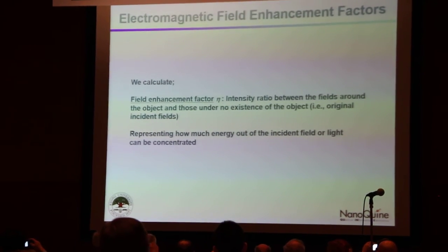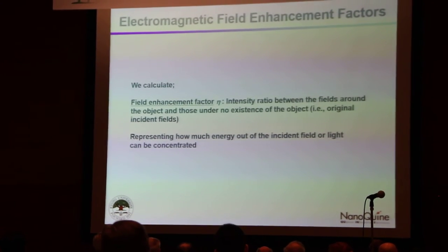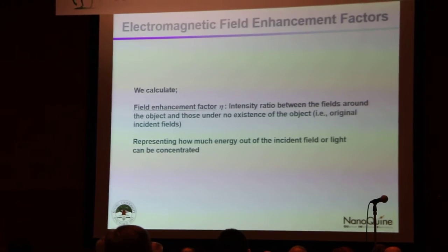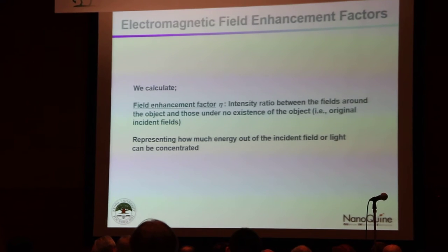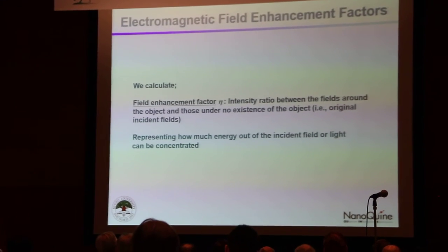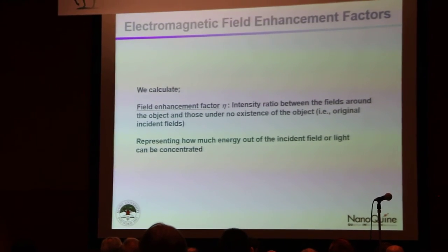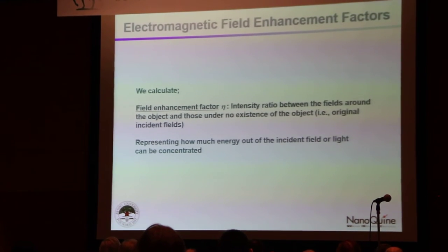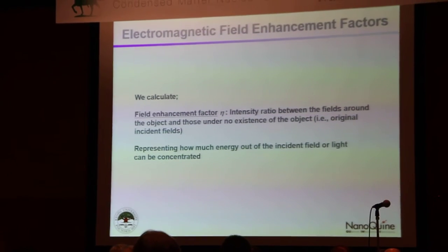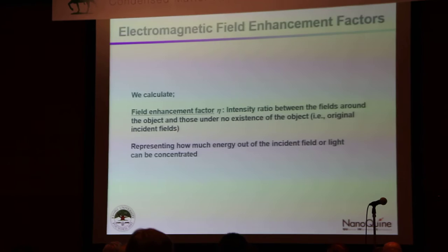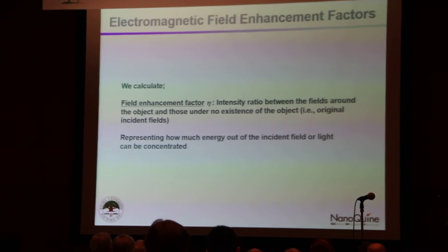I calculated the field enhancement factor around metal nanoparticles in the electromagnetic field of incident optical light. The field enhancement factor is defined as the intensity ratio between the field around objects based on those under no existence of such objects or metal nanoparticles. So we can know how much energy is enhanced by the existence of metal nanoparticles.